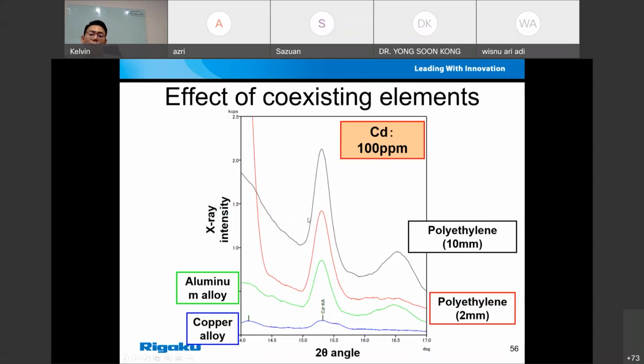Also, as is suggested here, you can see the cadmium in these 4 different types of medium: aluminum, copper, polyethylene, with different thickness. You can see the intensity itself is not constant, even though all of them contain about 100 ppm. So it is affected by what you have inside the system; it is not a constant value. That's why it is very important that you use a standard which is similar to what you have in your sample.